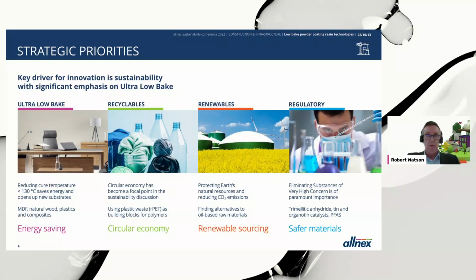When we think about powder coatings, where they came from, they were originally designed to cure at 180 to 200 degrees centigrade, which is still very much the case. And that means that the substrate that was to be coated with the powder coatings is always metal. If it's metal, it can be powder coated. But when we talk about ultra low bake, we're looking at how we can drive down the curing temperature and get down to 130 degrees centigrade. And there's a lot of research intensity going into this effort.